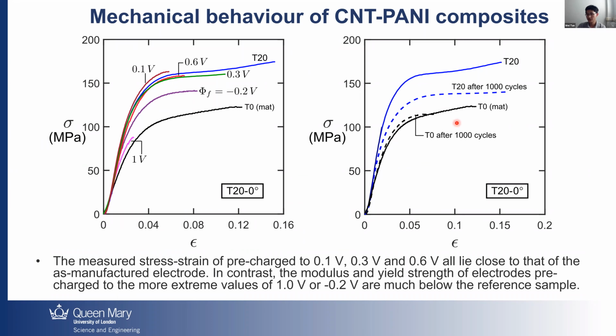And we can see actually after 1,000 cycles of the PANI, you can see there's some degradation happens. Therefore, the mechanical property also decreases. And for CNT mat without PANI after 1,000 cycles, you do not really generate too much difference.